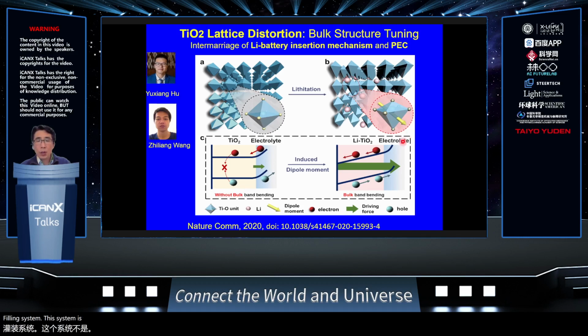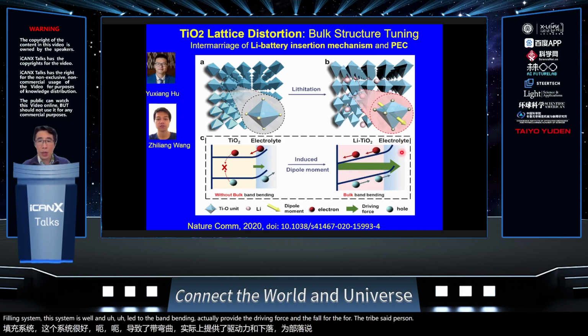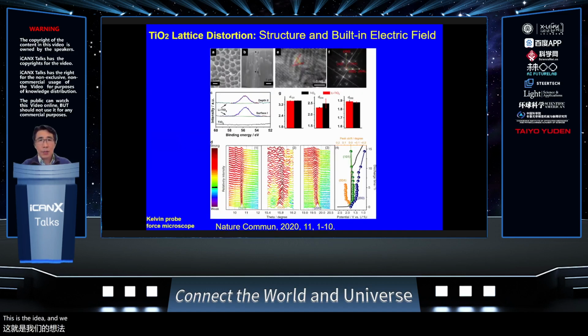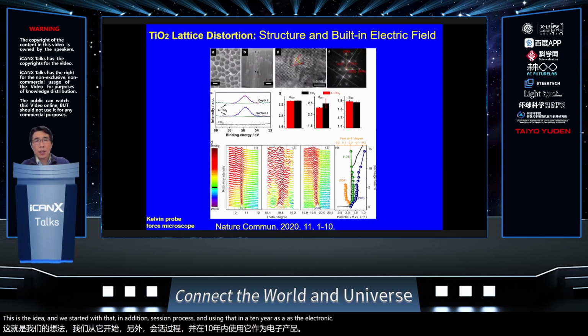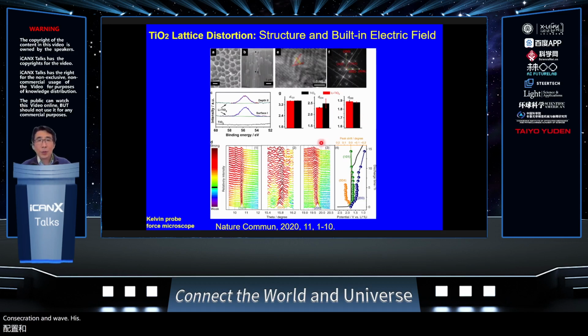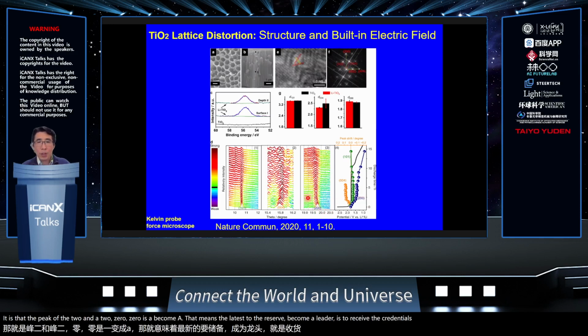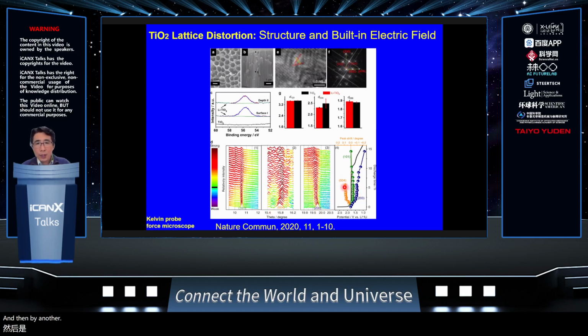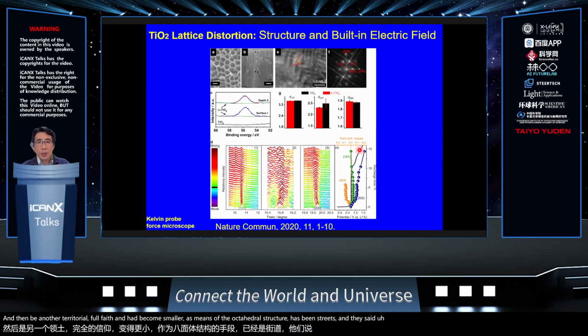This will lead to band bending, actually providing the driving force for the charge separation to happen more efficiently. That's the idea. And we started with the lithium insertion process, using the TiO2 as an electrode for the lithium-ion battery configuration. When we insert the lithium into the species, we can see that the 200 peak shifts to a smaller angle, meaning the 200 lattice becomes larger, and the 004 peak angle also becomes smaller. That means the octahedral structure has been squeezed, and that generates distortion.